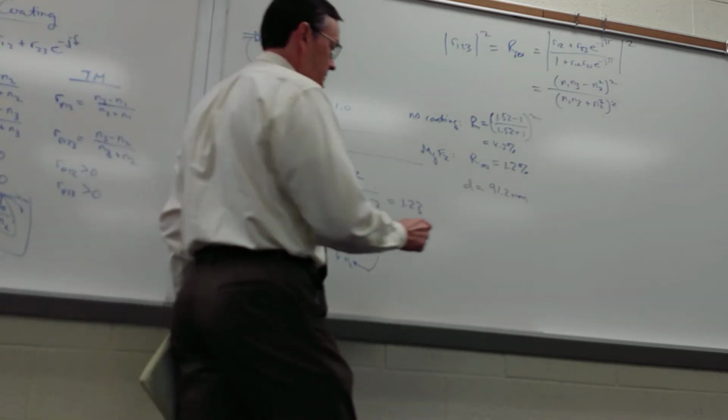I mean, that's what these thin film deposition tools and clean rooms are for. Put down thin films of materials, whether it's e-beam evaporation, RF sputtering, DC sputtering, thermal evaporation. Those are typically the methods that get used. You can do low-pressure chemical vapor deposition, but not for mag fluoride. And then there are other deposition methods. But then it gets back to, when you do the thin film deposition, what's the morphology of the film that you get? And if you have a low surface energy or low energetic process, like, say, e-beam evaporation,